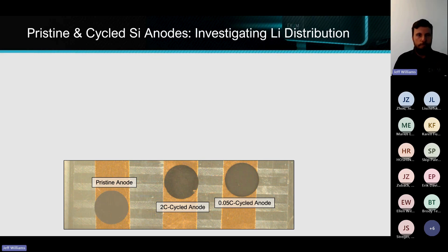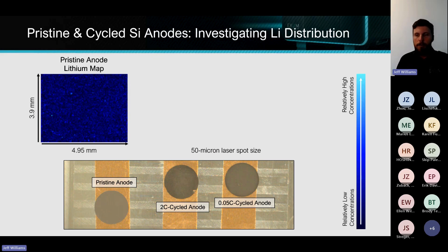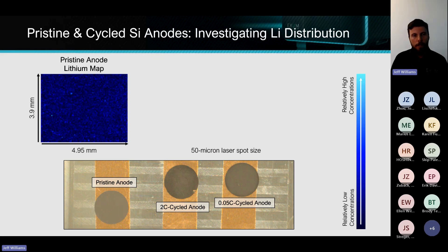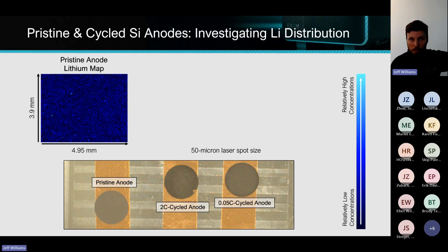And how is the electrolyte decomposing? On the pristine anode, using the same color scale — blue is very high, black is very low — we're showing maps of lithium. We see a very homogenous distribution of lithium that actually shouldn't have been there to begin with. They had a process control issue of having lithium present when they weren't supposed to, but it was homogenous in the pristine.